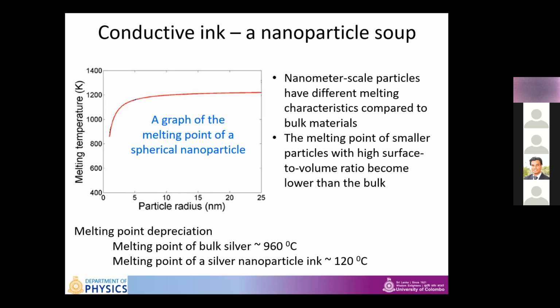What is interesting is that at smaller particle sizes, I'm referring to less than about 5 nanometers, the reduction in melting point compared to the bulk is significant. Bulk silver, for example, has a melting point of about 960 Celsius. But at nano dimensions, we can melt a silver nanoparticle at around 120 Celsius. That's a significant reduction in melting point. We call this melting point depression.